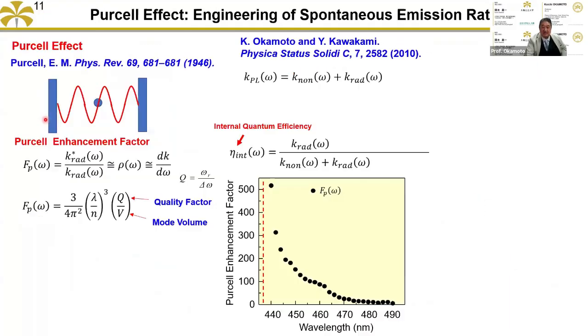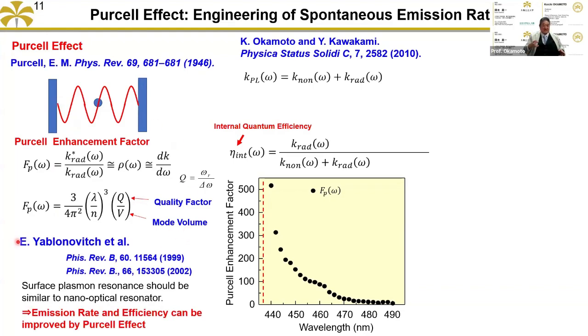Then that's the mechanism. The mechanism of the enhancement of the spontaneous emission is the Purcell effect. The Purcell effect was published in 1946. That's a very old paper, just a half page, a very small paper, but it describes a very important effect. If you put the light emitter inside a cavity, the coupling of the light emitter and the cavity enhances the spontaneous emission rate, and the emission lifetime becomes shorter. That enhancement factor should be proportional to the quality factor of the cavity and inversely to the mode volume. Then Professor Yablonovitch suggested that surface plasmon coupling is almost similar to such a resonator, and he predicted that the surface plasmon coupling should enhance the spontaneous emission rate.